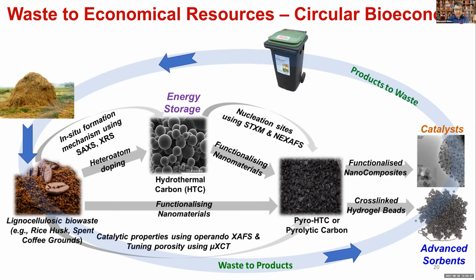And again, in situ XAFS is used to understand the properties at each step. But also another important factor which was missing, or rather something that could not be done in natural systems and which could be done in these engineered materials, is tuning the porosity. So we can use different techniques to try to create hierarchical porous structures of these carbon materials. And that is something that we routinely probe using tomography. That's something that I'm not showing here.